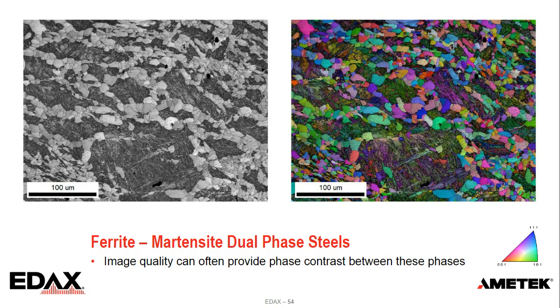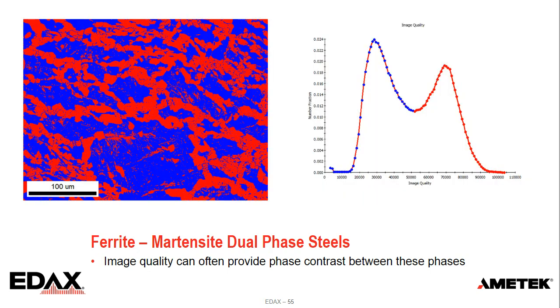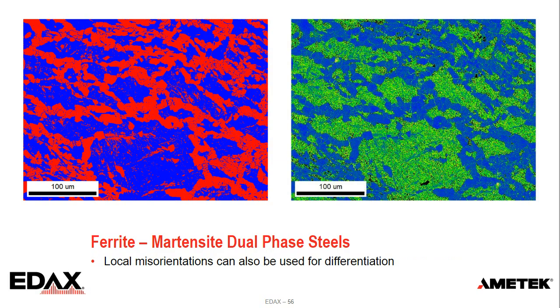But this is just an example showing how image quality can change. We can color the image quality this way to show it. And we can also see it again with local misorientation. So the martensite generally will have a little bit more misorientation.